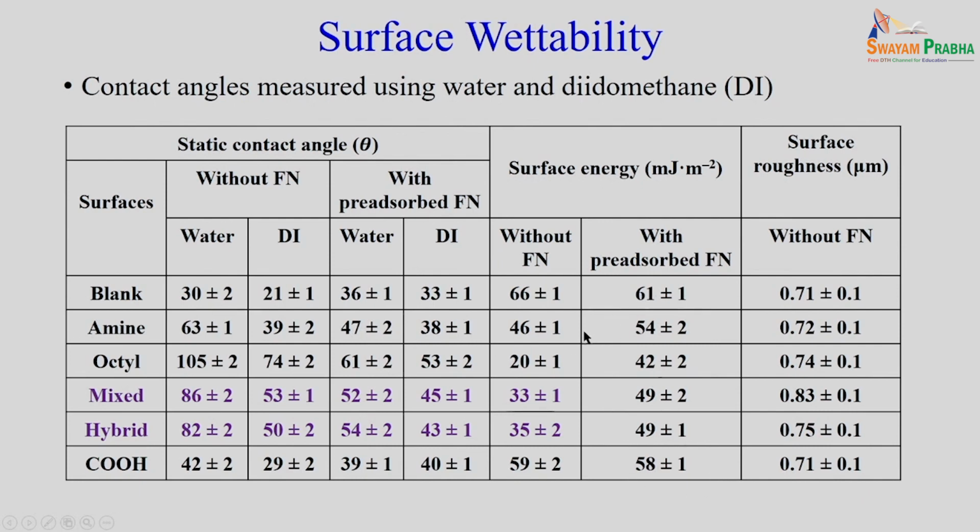And you can see there is again a change in the surface energy after the protein adsorption. For the hydrophilic surface there is a slight decrease in the surface energy after adsorption, here again there is a decrease in the surface energy after adsorption, but in case of the hydrophobic or moderately hydrophobic surface, there is an increase in the surface energy after the adsorption.